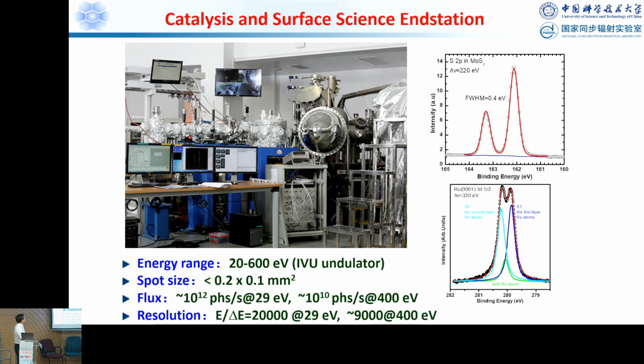Okay, and you see this undulator. Because our ring is only 800 MeV, I have to use the IVU, the so-called in-vacuum undulator. Now it can bring the energy up to 600 eV. So we do have this high resolution. You see here, ruthenium 001. We can find the surface component, bulk component, and this sulfide 2p. You can see the peak very well resolved. And with this beam line, we have a relatively small beam size and also relatively high photoflux.